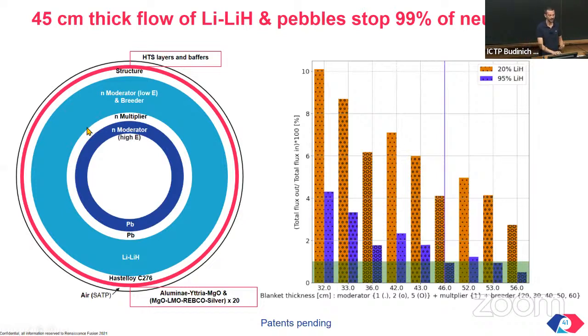Hence the idea of, instead of just lithium, using a solution of lithium hydride. Okay, much more effective at slowing down the neutrons, as I said. And eventually the lithium absorbs them and produces the tritium. Although hydrogen is a good attenuator at medium and low energies, you need an additional material to moderate at high energies. This serves a dual purpose. It also multiplies the neutrons. So there is an n-to-2n reaction.